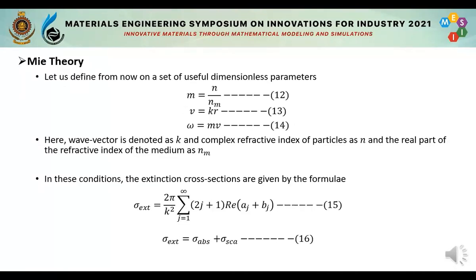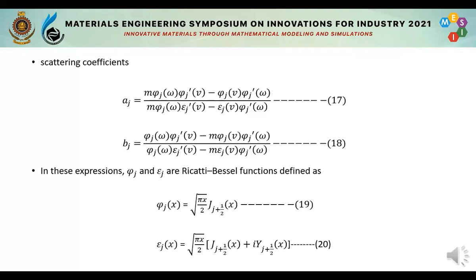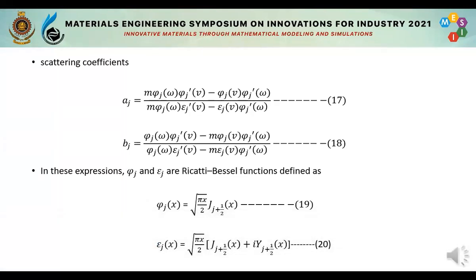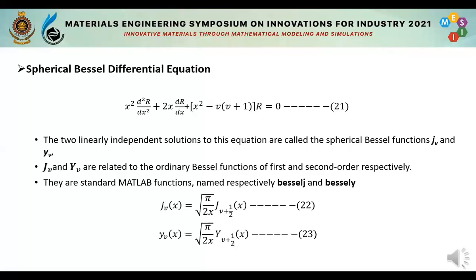The extinction cross-section of a small spherical particle immersed in a medium with a given refractive index at a given wavelength can be described using Mie theory. We can use it to calculate the extinction cross-section of nanoparticles. The scattering coefficients are given in terms of Riccati-Bessel function solutions, which can be described as mentioned. Then we selected the MATLAB program for calculating the extinction cross-section of nanoparticles. Solutions of the Riccati-Bessel function were not included as MATLAB standard functions, but solutions of the ordinary Bessel function were included as MATLAB standard functions. These are the solutions of the spherical Bessel function obtained from the solution of the ordinary Bessel function.